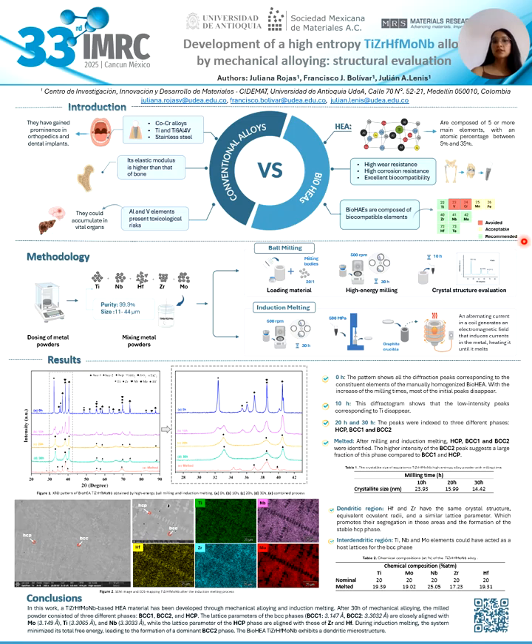For this reason, the objective of this research is to develop a new bio high entropy alloy with the constituent elements titanium, zirconium, hafnium, molybdenum, and niobium using two different methods, high energy milling and induction melting. To carry out both processes, the metal powders titanium, zirconium, molybdenum, niobium, and hafnium were dosed in an equiatomic ratio of 20%. Then they were mixed manually.